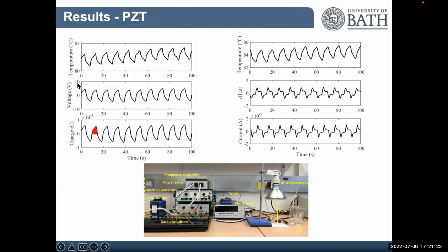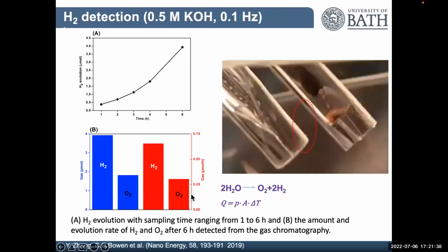And so this is a PZT lead zirconate titanate element, changing a few degrees C, 2 or 3 degrees C in temperature, but easily developing 5 volts. And so that was able to produce the hydrogen by the water splitting. But it's very small levels of hydrogen because it's small levels of charge on the surface. I think there's some bubbles here.